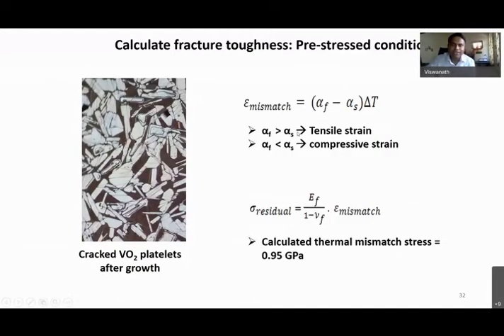Finally, we found the reason for such low fracture toughness values. You can see this is vanadium dioxide grown on a quartz substrate. The growth temperature is typically around 900 degrees Celsius. There are many of them already having cracks.